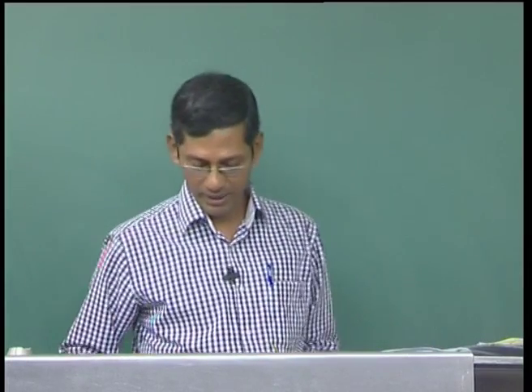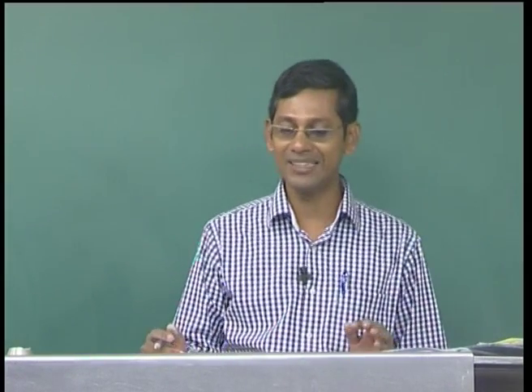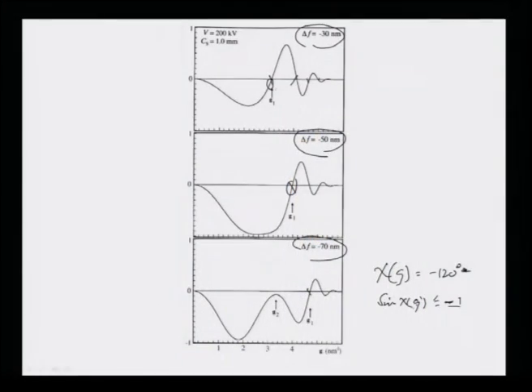Now, as we have discussed and shown you, in the transfer functions we normally do not take anything beyond this first 0, beyond this g1 value, which is basically of no use to us. But whether this is really true or not gives us the new concept called envelope damping functions. So plots of this Tg, or say chi g, chi g is also related to Tg, versus g, as you can see here, can they be extended from this first 0 to the other values?